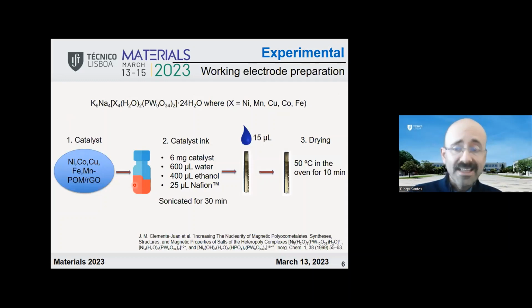How do we do the experiments? So basically, we first produce the materials, then the POMs are put together with the conductive carbon in a composite. The material we selected for carbon was reduced graphene oxide. Reduced graphene oxide is very used in electrocatalysis due to its high electronic conductivity and very interesting properties. So we prepared different composites between RGO and these different POMs.